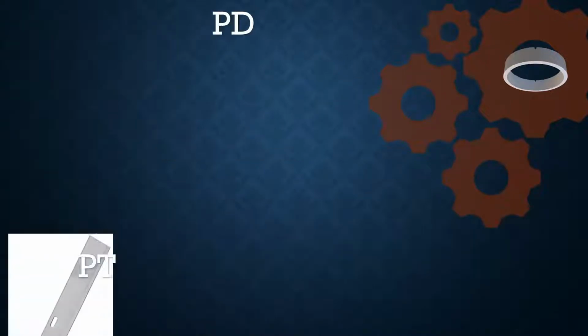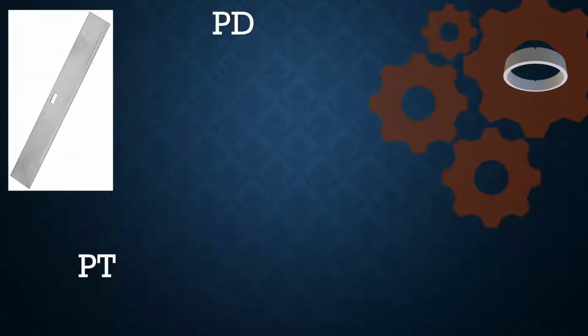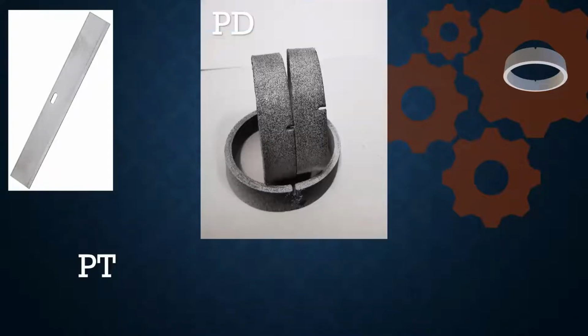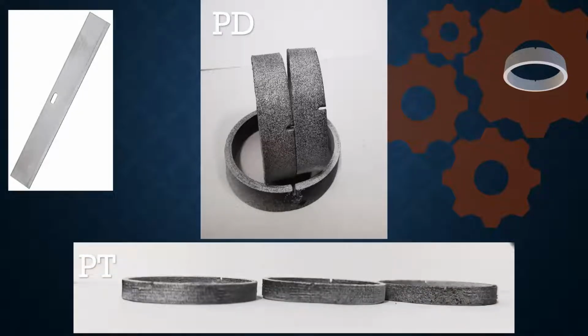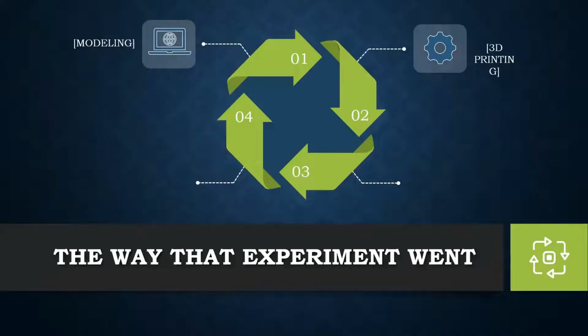The crack was applied to the test specimen with a blade whose thickness is about 0.5 millimeters with the help of a hammer. After applying the crack to the samples, a stochastic pattern was applied with the help of matte white and matte black spray. And the specimens prepared in this way are suitable for testing.